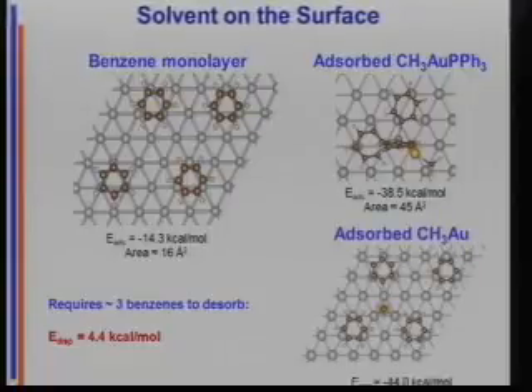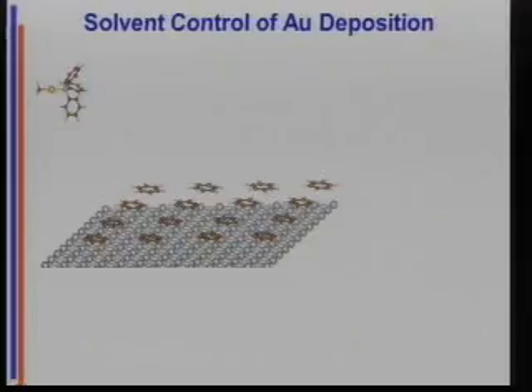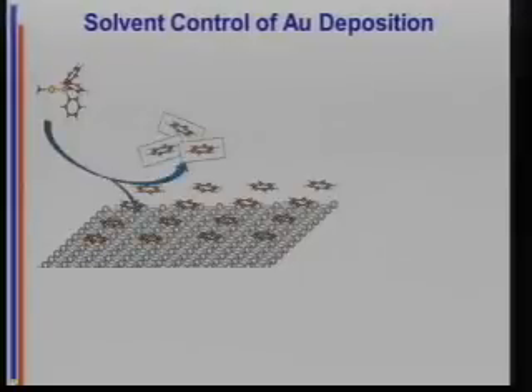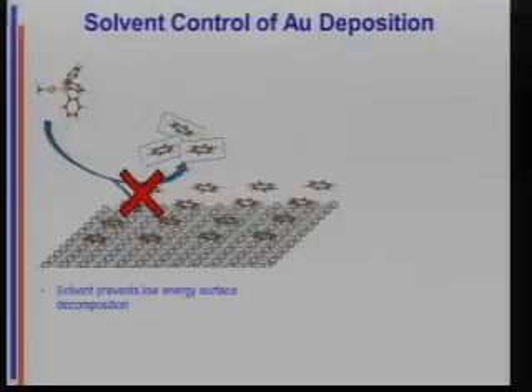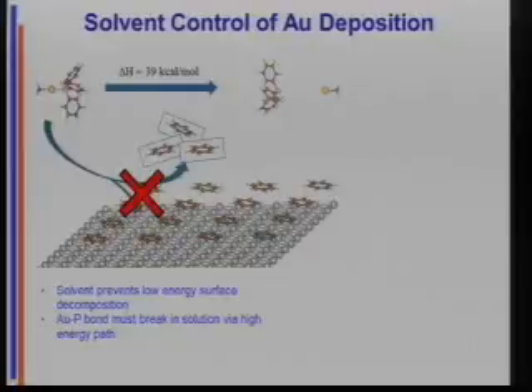But if you look at methyl gold fragments, they'll fit in between the benzene. So you can put methyl gold down without having to desorb benzene. Now we start looking at solvent control, because if you try to bring this in and displace 3 benzenes for it to have room, that doesn't happen because it's uphill. Instead, what we have is dissociation of the phosphine in solution.